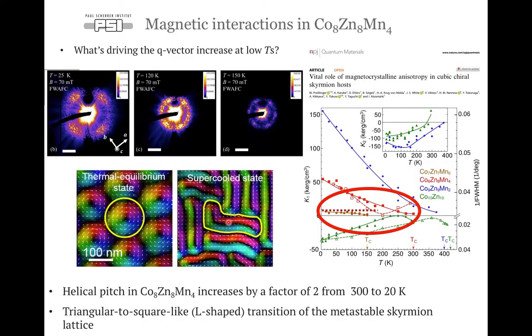Another topic I would like to discuss is magnetic interaction in another cobalt zinc manganese alloy with the lower manganese concentration, cobalt 8 zinc 8 manganese 4. And the question is, what's driving the Q vector increase at low temperatures that I have also mentioned a few slides ago. Again, here we can create a metastable Skyrmion lattice by field cooling, and it goes from triangular Skyrmion lattice arrangement into the orientationally disordered lattice at intermediate temperatures, and at low temperatures it changes the Skyrmion shape and forms the L-shaped or Tetris-like structure, a supercooled state.